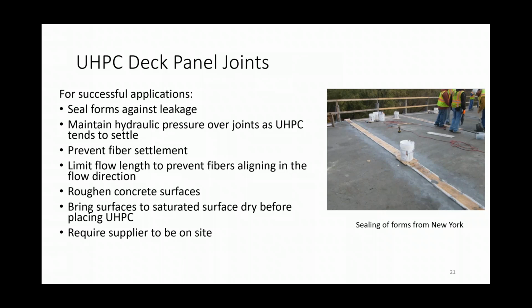And then just like any application, actually, with connections, roughening the concrete surfaces helps, so that if it's a deck panel to deck panel joint, having a roughened surface on those shear keys helps. And also very important, again, to bring the panel joints or whatever joint it is to a saturated surface dry condition before placing UHPC really makes a big difference.